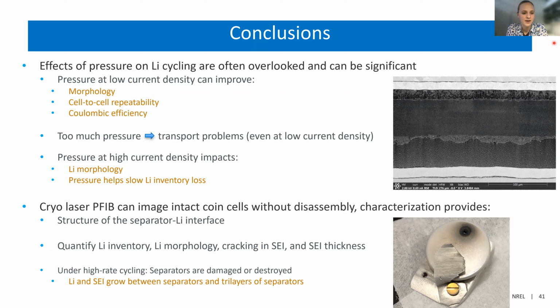The pressure for high current density did impact the lithium morphology, and the pressure did show to slow the lithium inventory loss, but there's still a lot of work that needs to be done there to stabilize that lithium morphology.